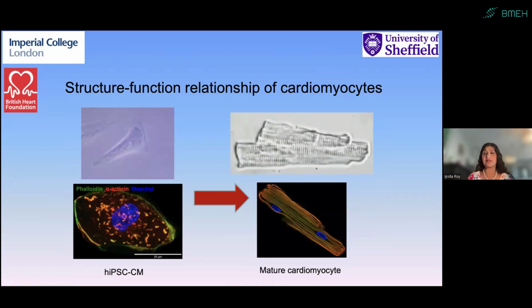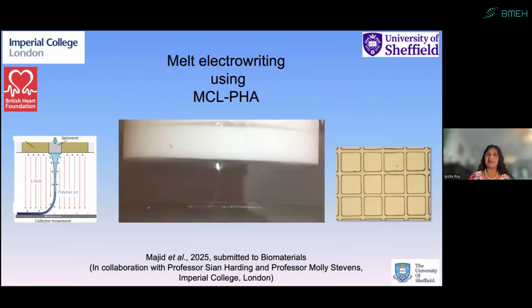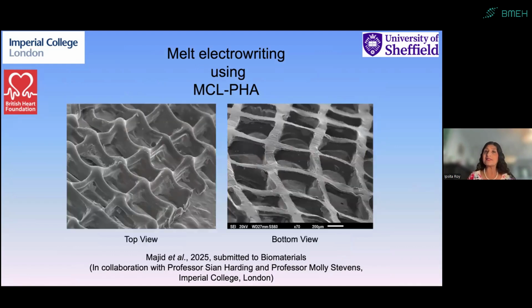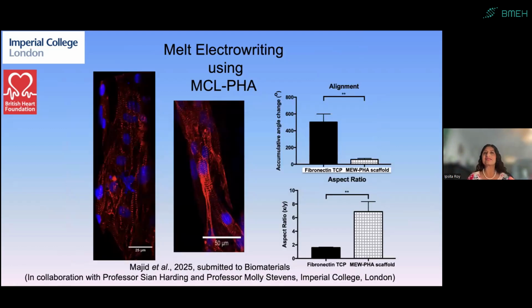So what we tried to do is we used the iPSC-CMs, but took medium chain length PHA that we had melt electrowritten. And after melt electrowriting, these are the structures we obtained, which means we had long and thin struts on which the cardiomyocytes could sit and elongate and therefore mature like a normal adult cardiomyocyte. And that's exactly what we saw.